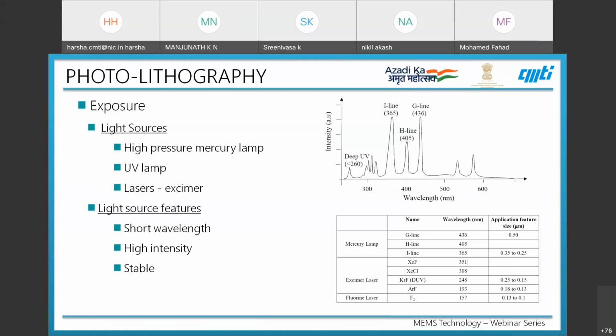On the right hand side, we can see the comparison between different light sources, their wavelengths, and application feature size in micrometer ranges. If we use a mercury lamp with the i-line of 365 nanometers, we can go as small as 0.35 to 0.25 microns, although practically most systems give a 1 micron feature size even today. For direct writing onto the wafer, we can use an excimer laser or a fluorine laser, depending on the feature size required, ranging from 0.1 to 0.25 micron with the excimer laser.